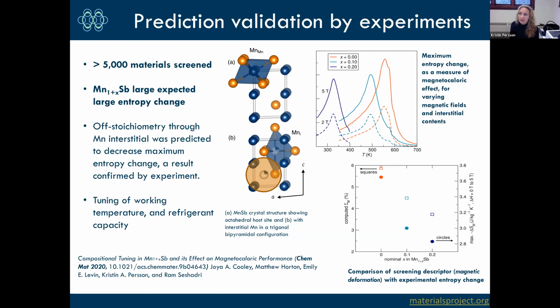So as we calculated and thought that this one should be fairly promising, the Seshadri group went about making the material and testing it. And indeed, it is a magnetocaloric material. It had a high response. It's in its stoichiometric state, but it also incorporates non-stoichiometry. So you could put manganese interstitially in this material, which actually degrades the entropic switching, so less heat absorption, because you're now including an antiferromagnetically ordered manganese as compared to the ferromagnetically ordered ones on the original sites. But it also gives you a way of tuning the temperature, which is important. So it's a new member in the families of magnetocaloric materials. And I don't know if it's going to be technologically important, but at least, again, it's a new candidate. And it's interesting to see if people can optimize it further.